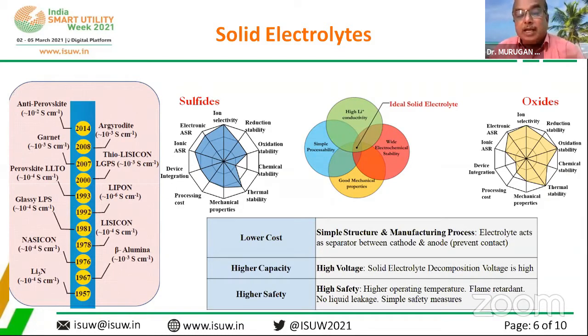Because we can make the plates roll to roll, that's the greatest advantage. Higher capacity, because of high voltage, you can think about the solid electrolyte standing the decomposition voltage, which is really high. Safety is very important in a battery. Higher operating temperature, you can think about 60, 70, 80, even 100 sometimes. A flame retardant, no liquid leakage concept, and these things make this an active research area.